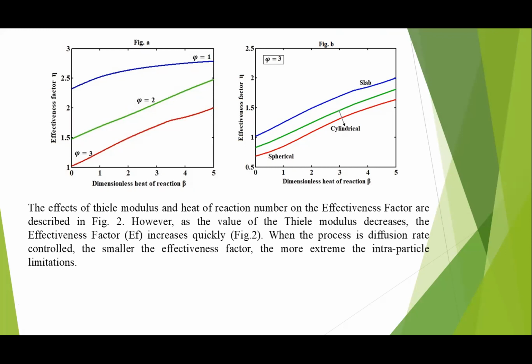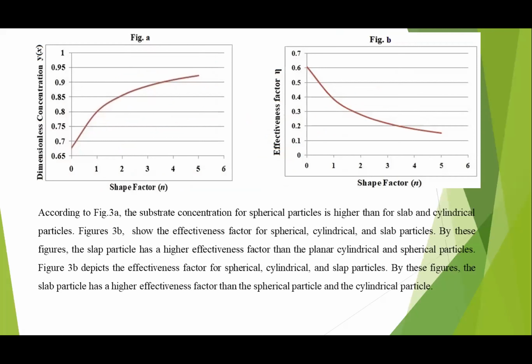When the process is diffusion rate controlled, the smaller the effectiveness factor, the more extreme the intraparticle limitations. These next figures illustrate that the substrate concentration for spherical particles is higher than for slab and cylindrical particles. They show the effectiveness factor for spherical, cylindrical, as well as slab particles. By these figures, the slab particle has a higher effectiveness factor than the cylindrical and spherical particles.